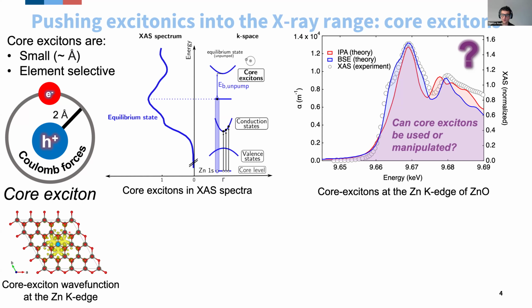And yeah, in case you didn't know, these core excitons are actually very present in the X-ray absorption spectra of many semiconductors. And one way to highlight that they're actually present is by doing calculations that I'm showing here in the top right. So you see the experimental spectrum of zinc oxide at the zinc K edge with gray circles. And we can do two levels of theory on this spectrum. One is called the independent particle approximation, the IPA, where you neglect the formation of core excitons, and the Bethe-Salpeter equation in blue, where you actually explicitly account for excitonic interactions. And you can see how excitons actually lead to a much better agreement between experimental data and calculated spectra. So they are indeed present in the X-ray absorption spectrum of many semiconductors.